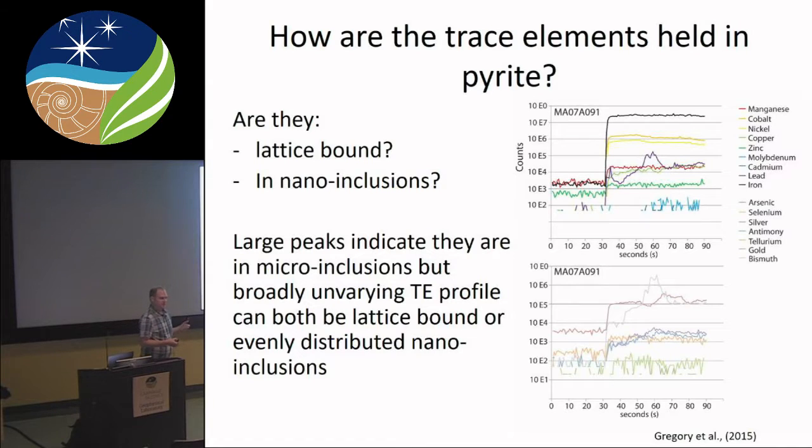So the argument is that if arsenic 3+ is substituting for iron, the iron site in the pyrite, for every 2 arsenics you have 1 void space just to balance the charge. That would then enhance the uptake of larger cations like gold or lead. Other arguments have been made that if arsenic is substituting in the sulfur site, that enhances the uptake of cobalt and nickel and other more iron-like elements. But if they're not actually in the structure, then we have to think differently about this.